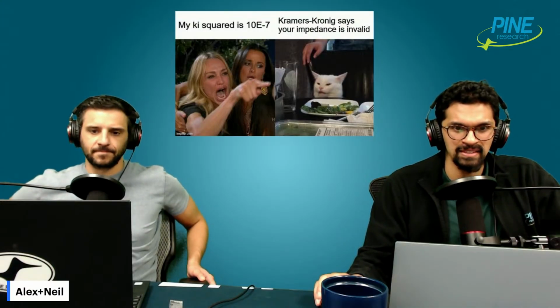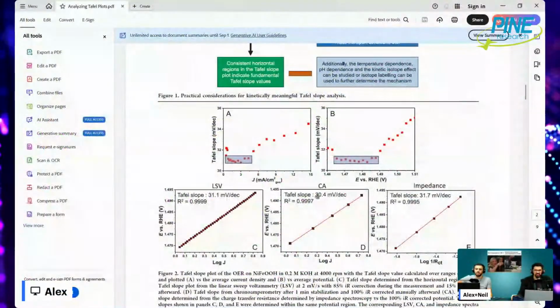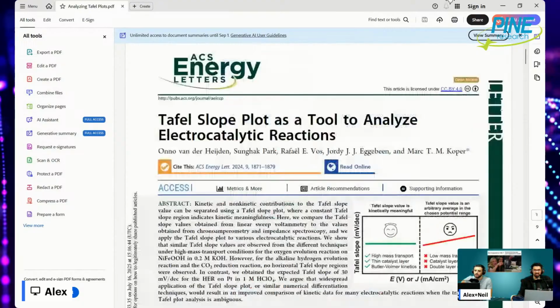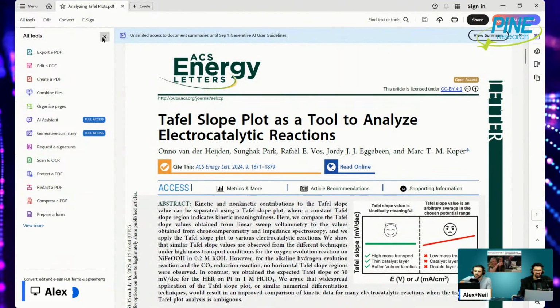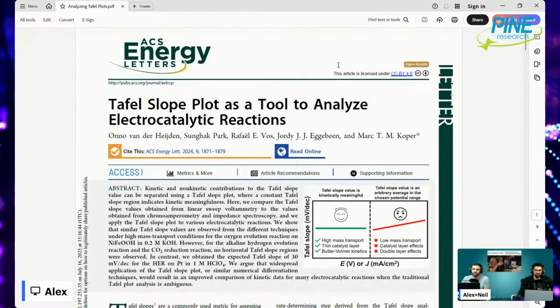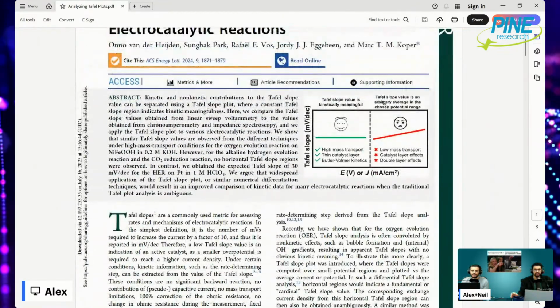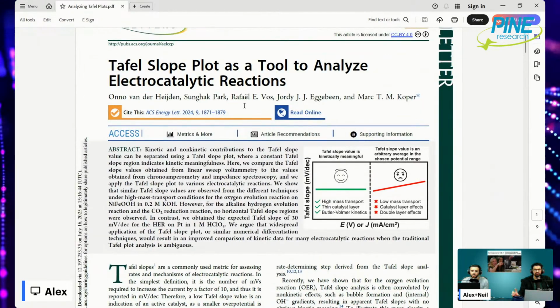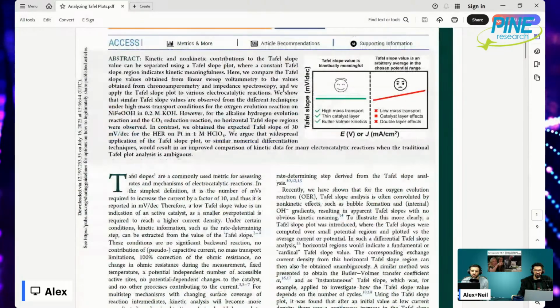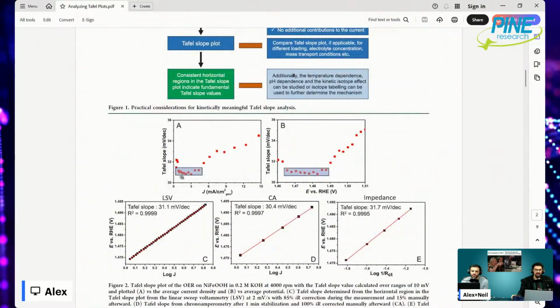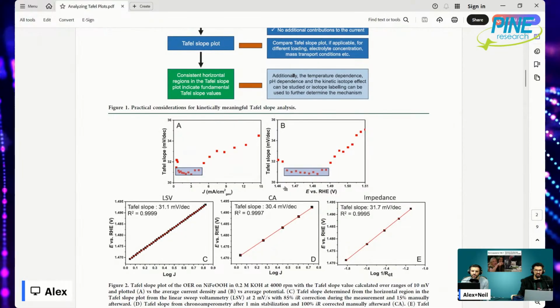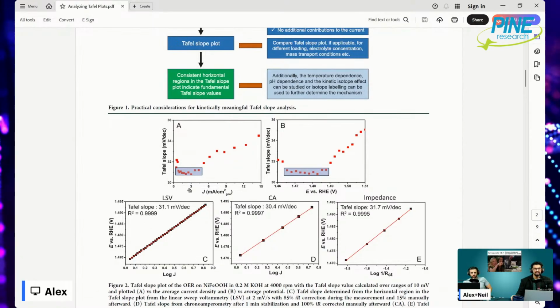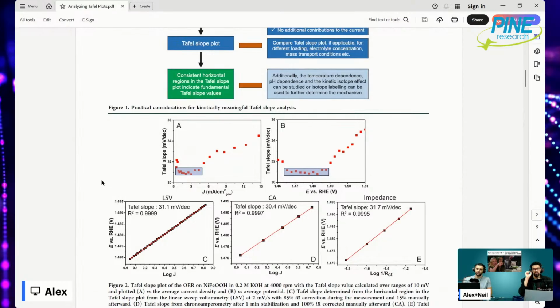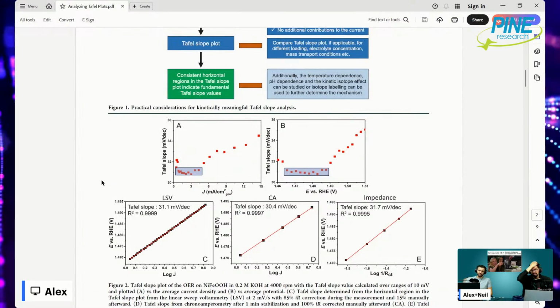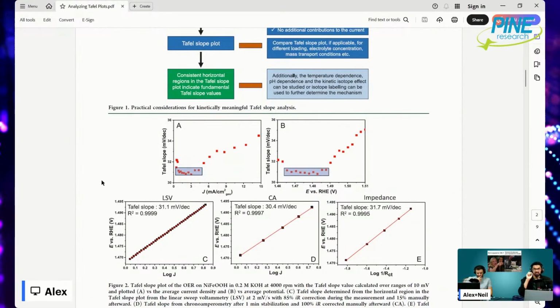There was a paper that I think actually has some really interesting things. One thing people should do, and this is from ACS Energy Letters. It's about Tafel plots and tools for analyzing electrocatalytic reactions. One thing that I think is a great thing people should be doing, which I think is what this article is advocating for, is you should plot the Tafel slope as a function of current density. So the idea is that you're actually calculating the Tafel slope at small periods, like 10 millivolt periods, or even like 5 millivolt periods next to each other.